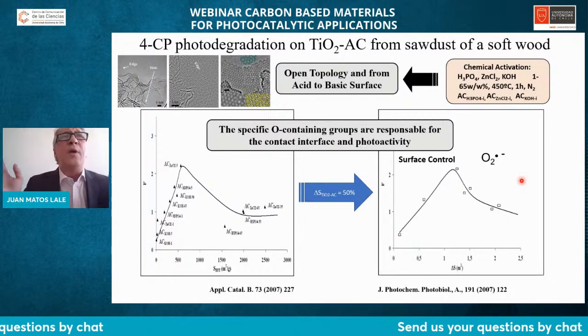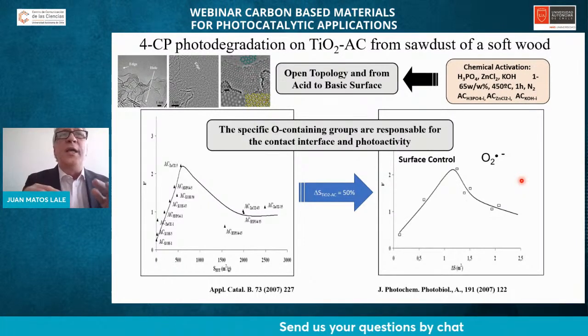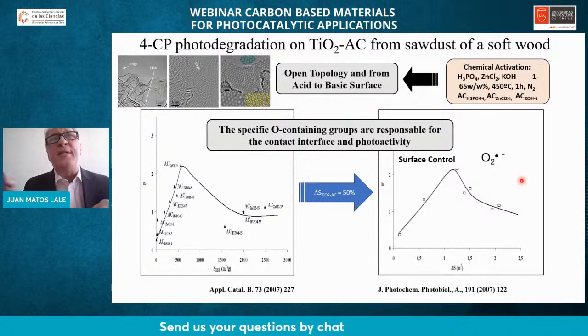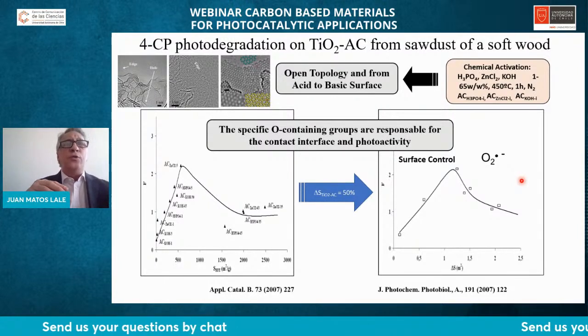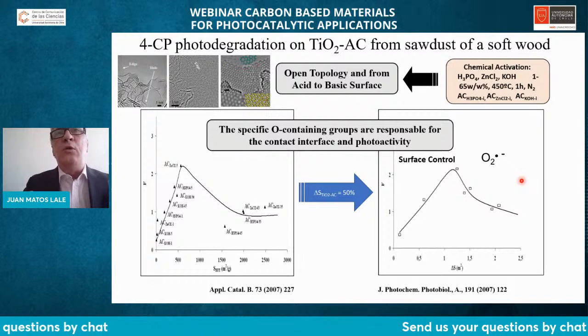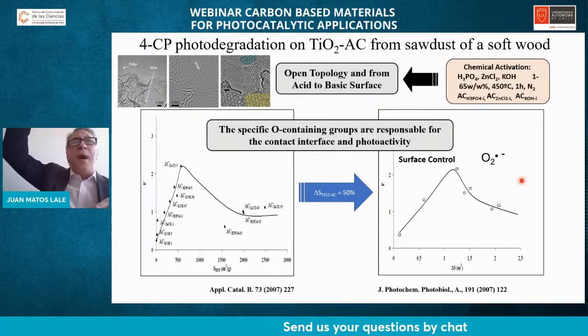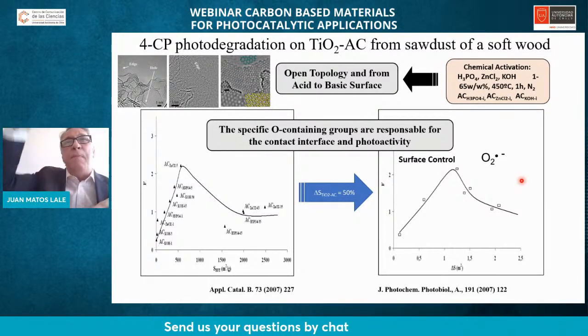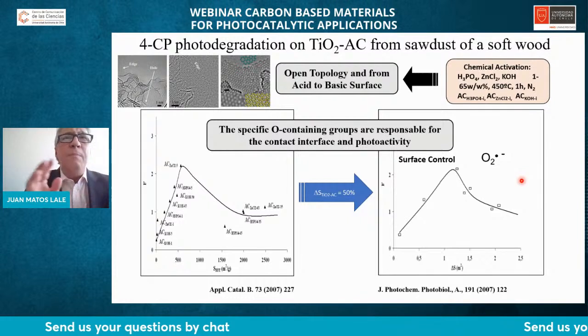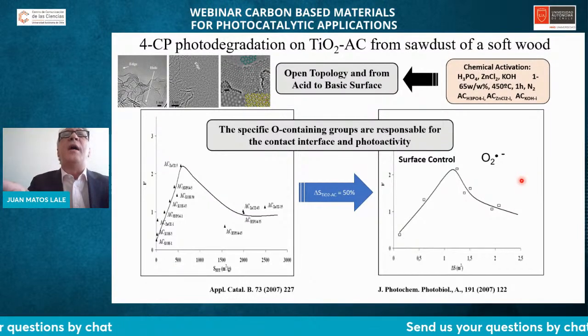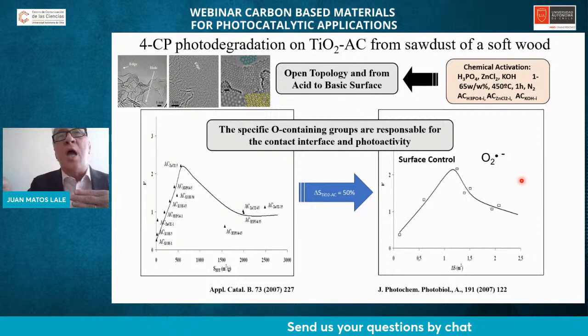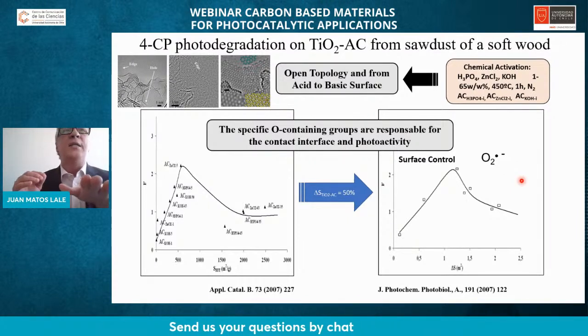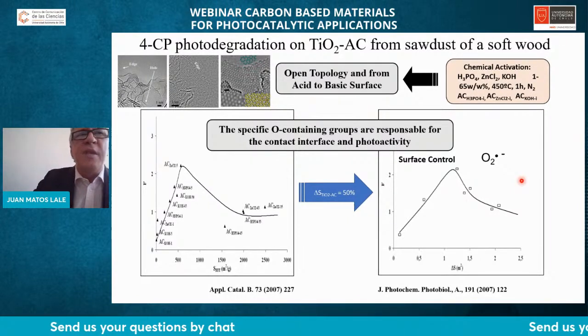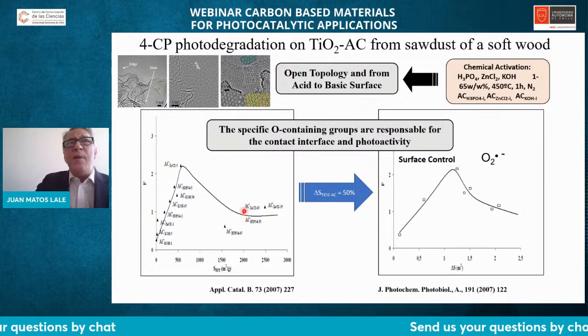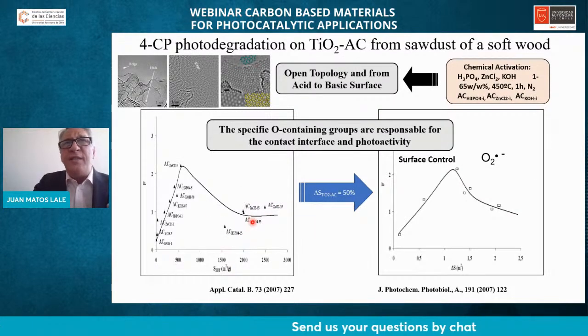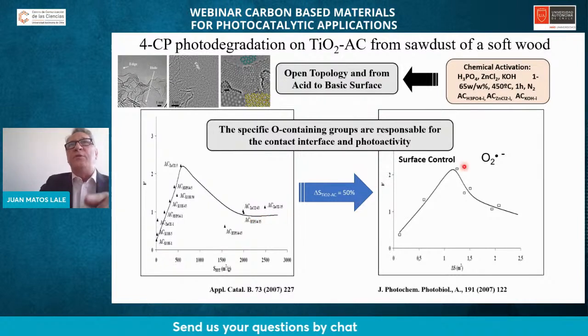And this is why, because we are in presence of quinones or carboxylic acid in the surface of carbon. And those functional groups are very easy to be excited from pi to pi and from pi to anti-pi orbitals by visible light. Are very easy to excite that, and we are dealing with the phenomena of the photoassistance of the catalyst. In this case, it doesn't matter. You have very high surface area carbon. It does not depend on that. It depends on the surface control.